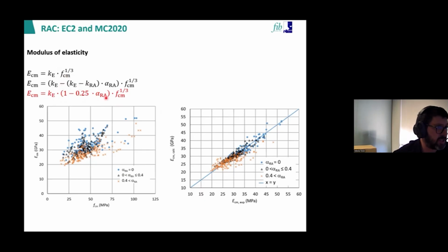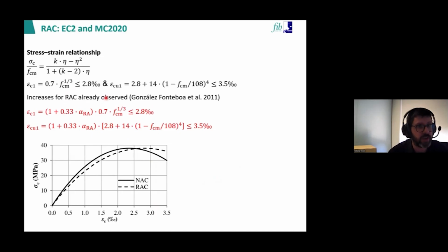Remember that alpha goes up to 0.4, that you can use it. So actually it's a 10% reduction. It's not so dramatic when you are within the limits of Eurocode. Stress-strain relationships, literature shows an increase in both the peak and ultimate strain. So there are some increases of 1 plus 0.33 alpha RA for the peak and ultimate strain.